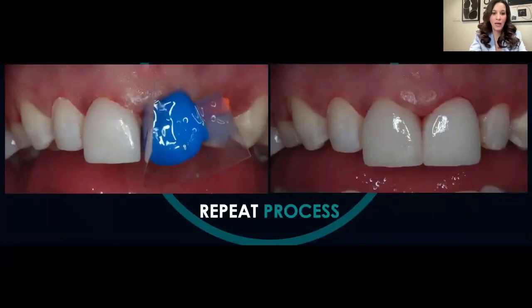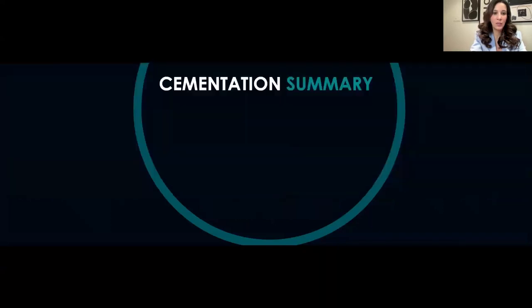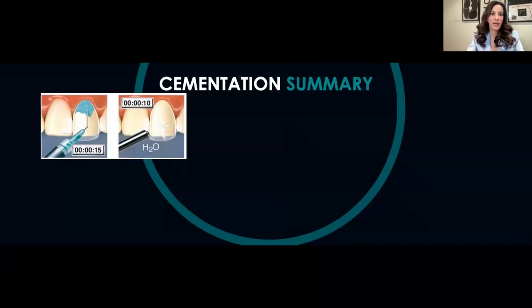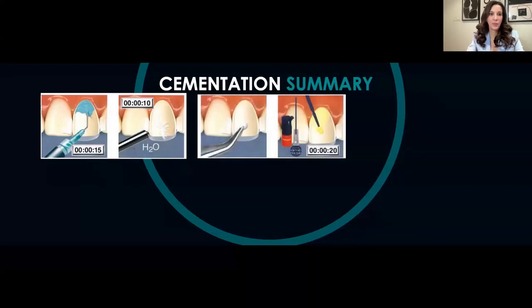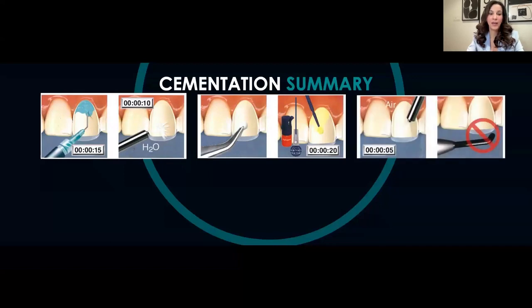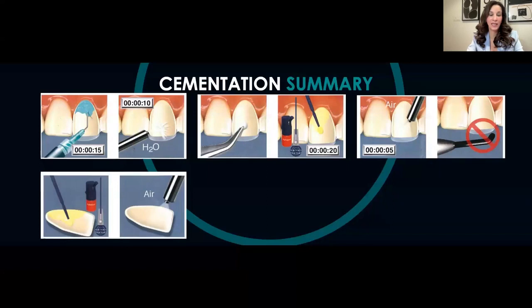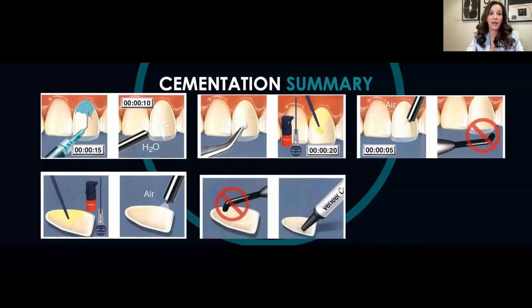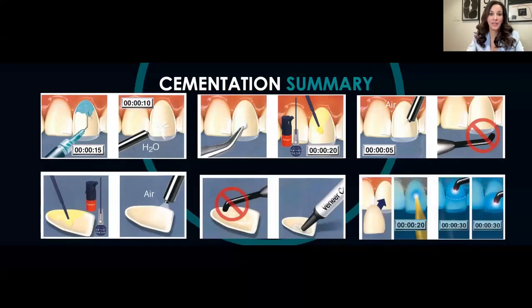And so to summarize, for cementation, you want to etch your veneer, etch the tooth, rinse it off, apply a bonding agent to the veneer and to the tooth, and depending on the manufacturer, either light cure or not light cure the resin, the bonding agent. Then you apply your resin cement and seat it onto the tooth. So that, in a nutshell, summarizes how I bond porcelain veneers.